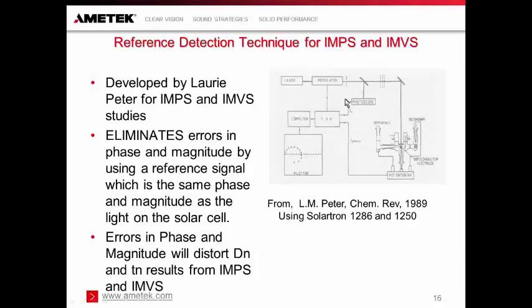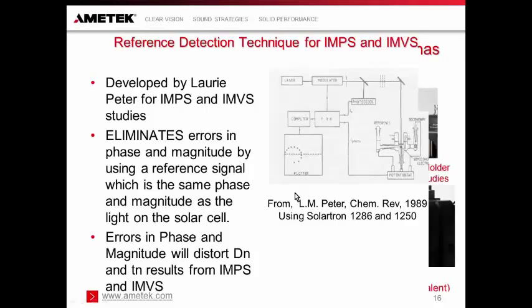And therefore, we compare the measured light, the measured phase and magnitude of light at the photodiode with the response from the cell. Because at high frequency, what will actually happen here is that the modulator will attenuate and introduce phase shift of the frequency response analyzer generator signal. And this will then introduce errors in phase and magnitude when we measure the IMPS and IMVS response of the cell. So if we measure this reference signal, it's in precisely the same phase and magnitude as the input to the device under test. And therefore this eliminates phase and magnitude errors. Errors in phase and magnitude will distort the effective diffusion coefficient and effective electron lifetime results from IMPS and IMVS. So this is a critical part of the system.